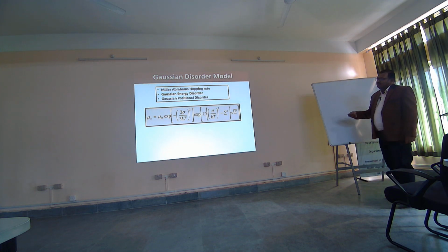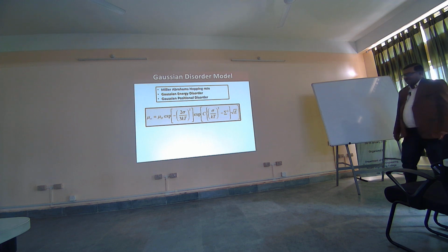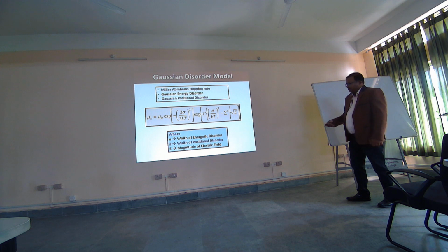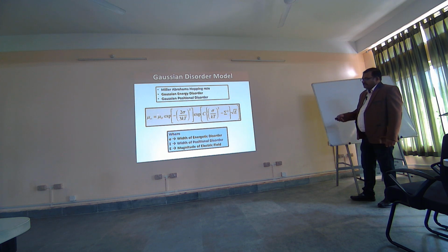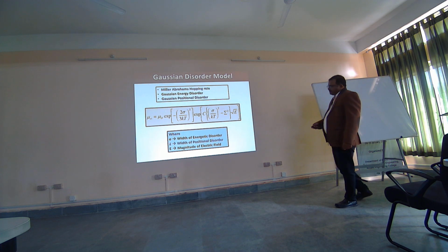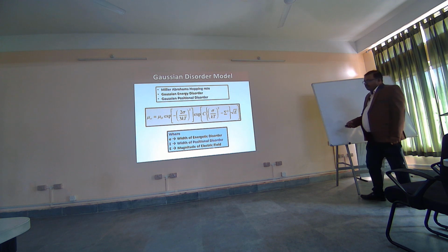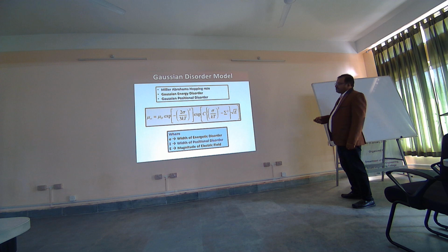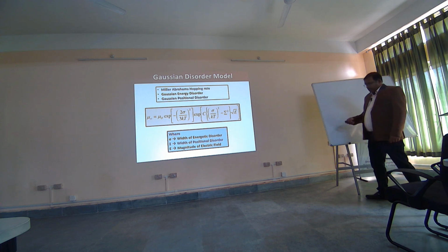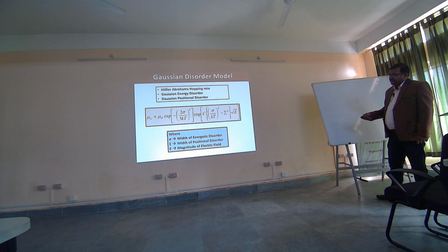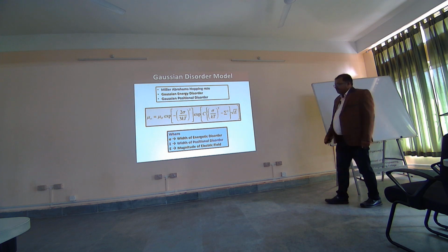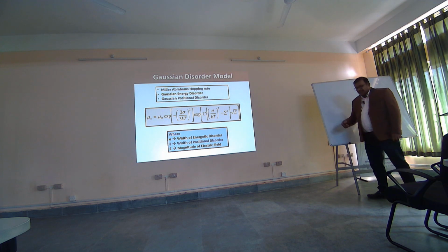And this is another disorder model which is often used to explain how the charge carrier transport happens. I'll again not go into the details of it, but what is important here is that the overall mobility is basically, so this factor sigma is the width of energetic disorder, and then this summation sign is referring to positional disorder. So this is energetic disorder, positional disorder, and this term is taking care of both these things. And if you see, the mobility typically follows some kind of square root dependence on the electric field. Okay, and it is also dependent on the magnitude of the electric field. That is another very important point.